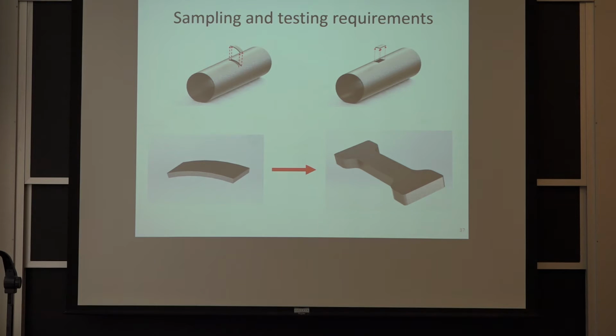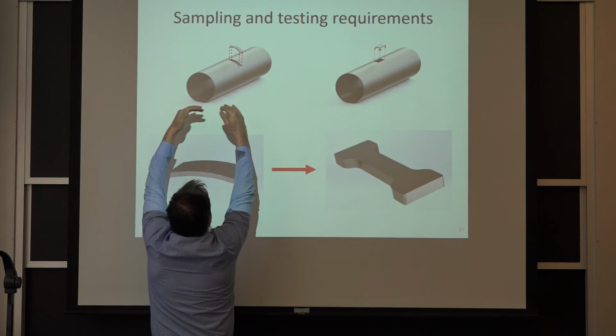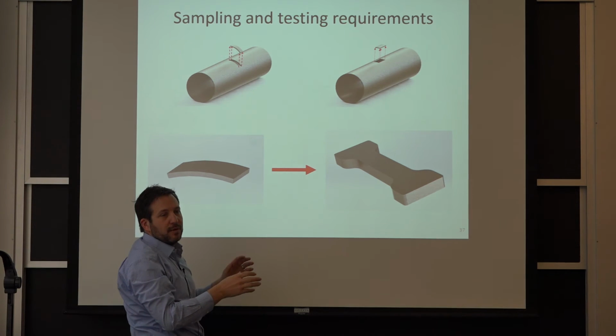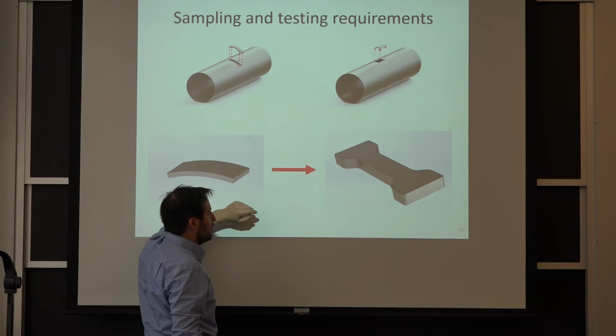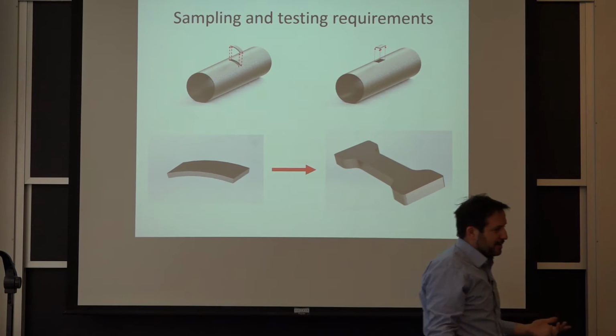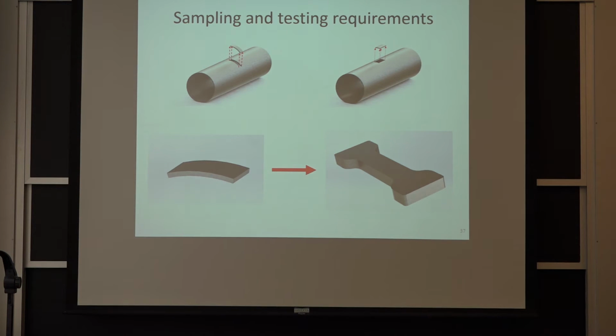Maybe we'll all agree here that it makes sense because you are interested in the resistance to a hoop stress. So you're more interested in the expansion resistance of the pipe than you are about the longitudinal properties. The counter side to that is you started from a flat sheet to make that pipe. So you had some cold forming involved on the surfaces. Then you flatten it back, you have more cold forming. So here is a composite response that you're getting from your test from all this forming history and the material itself. Which way is better doesn't really matter in the end because you have to meet the specification.